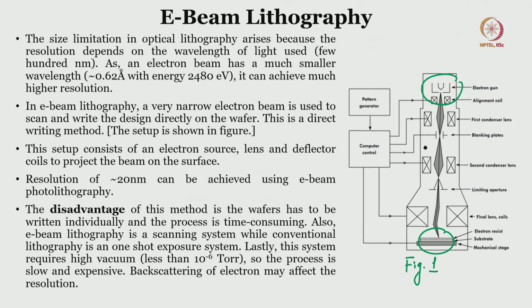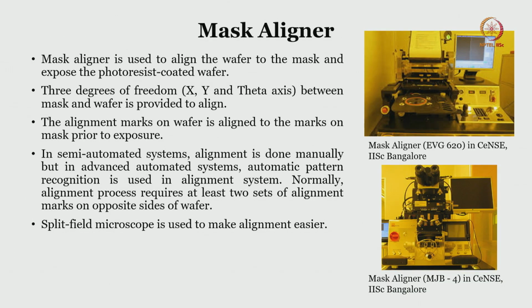Also, it is a scanning method, while conventional lithography is a one shot exposure. Finally, this system requires a high vacuum, about 10 to power minus 6 torr. So, the process is slow and expensive. Finally, the last thing that we need to understand in E-beam lithography is that backscatter of electrons may affect the resolution of the process.